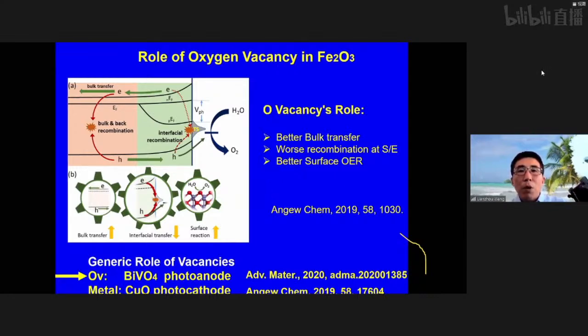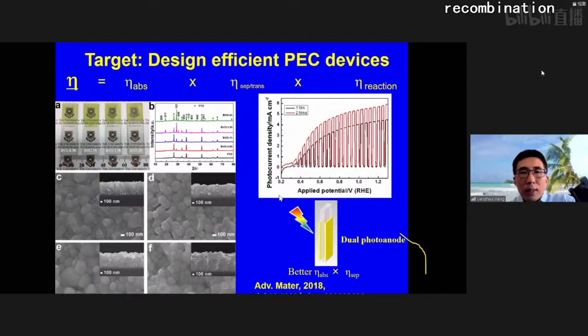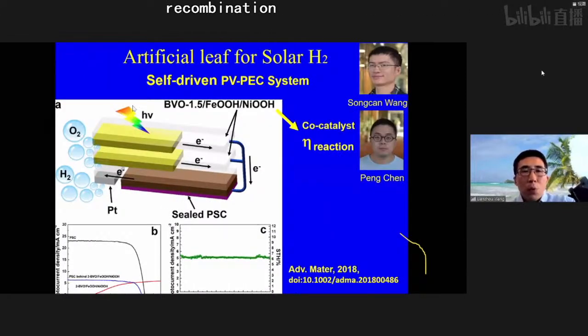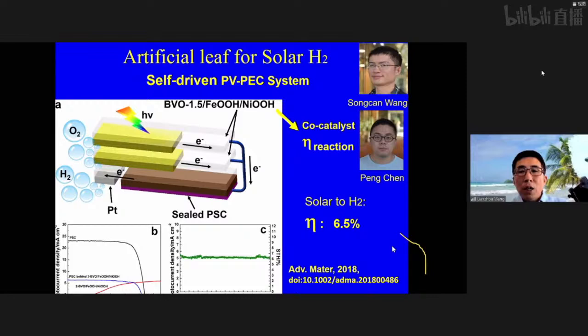for the PEC performance increase. But the final target is still to increase the overall efficiency in terms of water splitting. In this case, we used the bismuth vanadate electrode, a semi-transparent one, and we tried to achieve as high a photocurrent as possible. By using this as the electrode in combination with a solar cell, without any external bias, we found the system can produce hydrogen and oxygen at a relatively good efficiency of around 6.5%. This is a relatively good result for a PV-PEC tandem system.